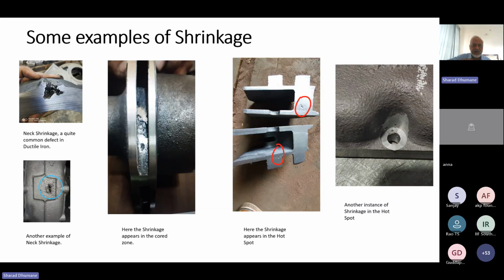Another interesting slide. Some examples of shrinkage defect. So many of these photos I have personally taken. So here you can see a neck shrinkage. This is quite common defect in ductile iron. Then below there is another neck shrinkage. It is exactly on the ingate or the riser neck. So there is no doubt that this is a neck shrinkage.